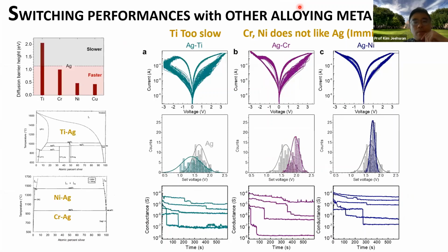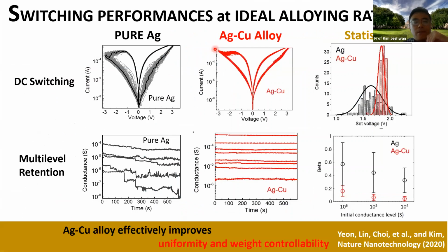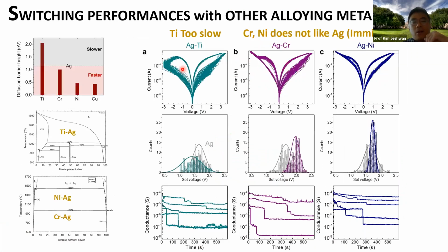So what is the switching behavior with a different alloying element? Except for the copper, as you can see, if you add titanium into silver, switching behavior is not different from just a silver device. The reason is that Ti does not diffuse inside the switching medium faster than silver, so silver is dominating here. And chrome and nickel do not mix well with silver, so switching behavior is also kind of random. So copper really works well for this.